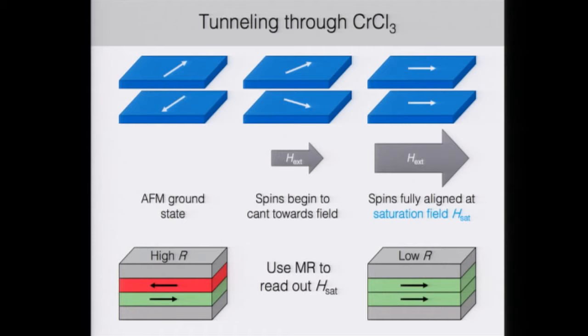So the basic idea here is that we start out in the antiferromagnetic ground state, which is the anti-parallel high resistance state. And then as we apply a magnetic field in a given direction within the AB plane, the spins in both layers will begin to cant towards that field. And once we reach the saturation field, the spins will be fully aligned. And so now we'll have a low resistance parallel state. And so we'll be able to use the magnetoresistance to read out where the saturation field is, because we should see a plateau once we reach this low resistance state.